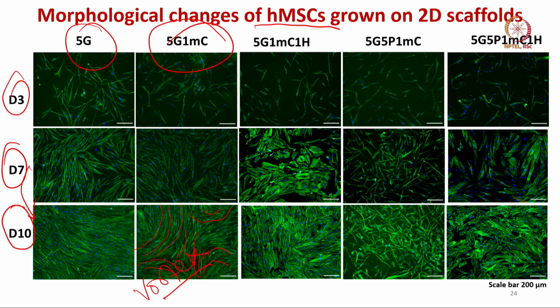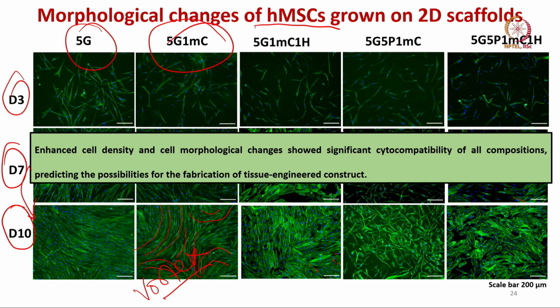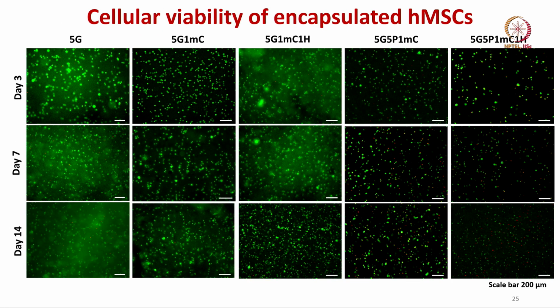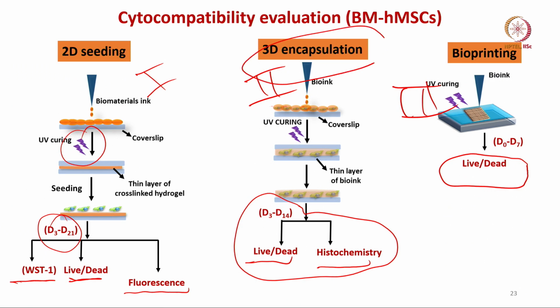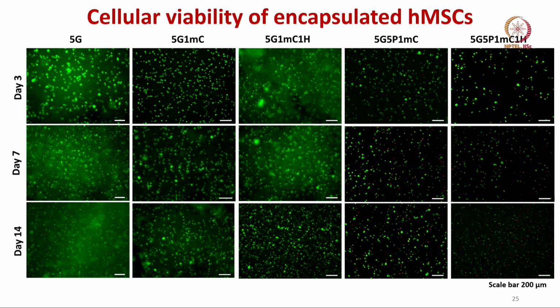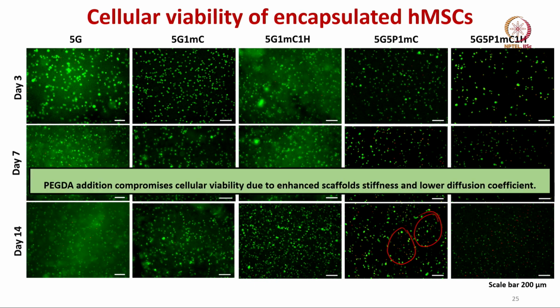When you see the blue nuclei, stained with DAPI, and the phalloidin stained cytoskeleton, it is very clear. Green is all cytoskeleton, and blue dots are all DAPI stained nuclei in the fluorescence microscope. Clearly, with these encapsulated HMSCs grown for different days from day 3 to day 14, in the live dead stained images you do see red dots here. That means cells are not alive. As I said, in 3D bioprinting it is always a challenge to maintain cell viability, and that was largely related to the large scaffold stiffness and lower diffusion coefficient.